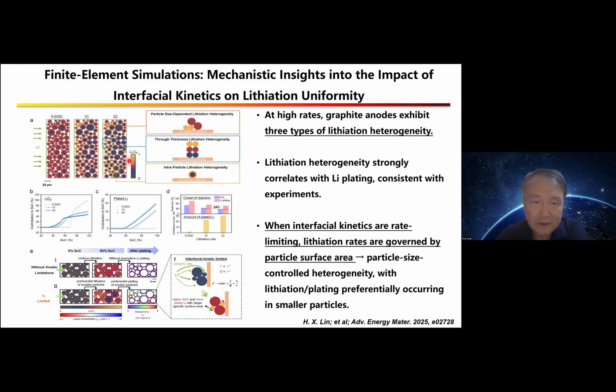Using finite element simulation, we found that when interfacial kinetics are rate limiting, lithiation rates are also governed by particle surface area. That means less surface area makes it easier to reach the fully lithiated state, and easier to form lithium plating. These are the issues we should consider.